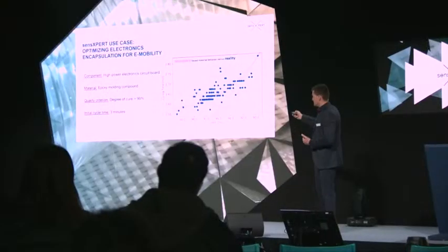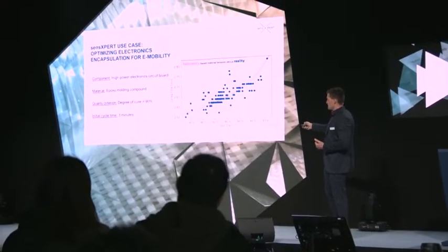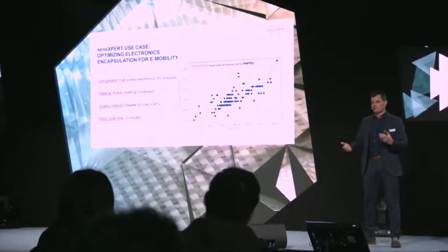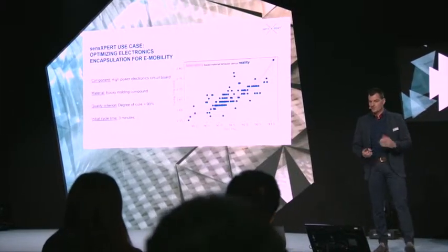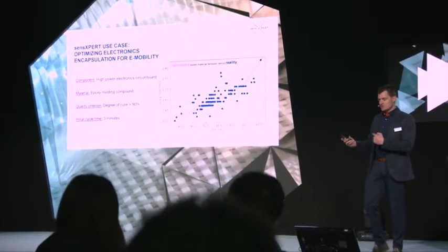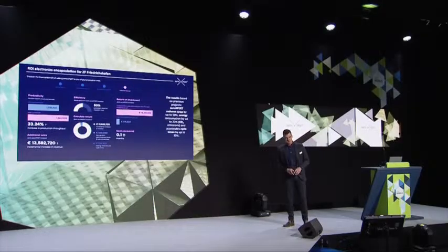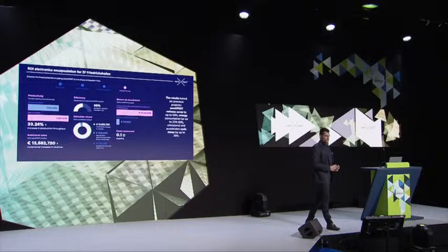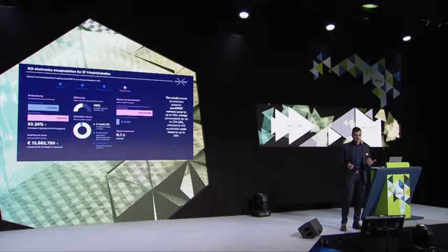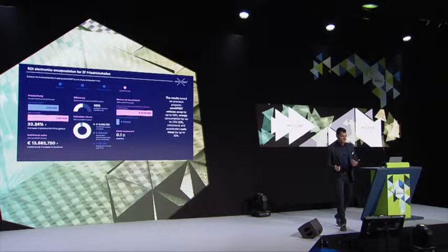And we can even say 3 minutes initial cycle time. We even have parts that are finished at almost 2.5 minutes. So a lot of cycle time that is getting lost. And here, we are talking about millions of parts every year. That, at the end, results in an efficiency increase of more than 30% if I can see what happens in the mold and I can react on that.